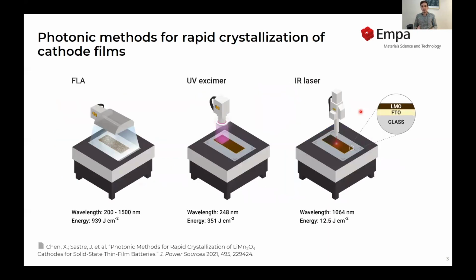So what we try to do in our work is investigate alternative methods for crystallization of cathode films, specifically photonic-based methods. So we compare three common techniques for crystallization: flash lamp annealing, UV excimer laser, and IR laser. Flash lamp annealing consists of a xenon lamp, which emits visible light, and it's pulsed in microsecond pulses. The visible light between 200 nanometers and 1500 nanometers gives an areal energy of around 900 joules per square centimeter.